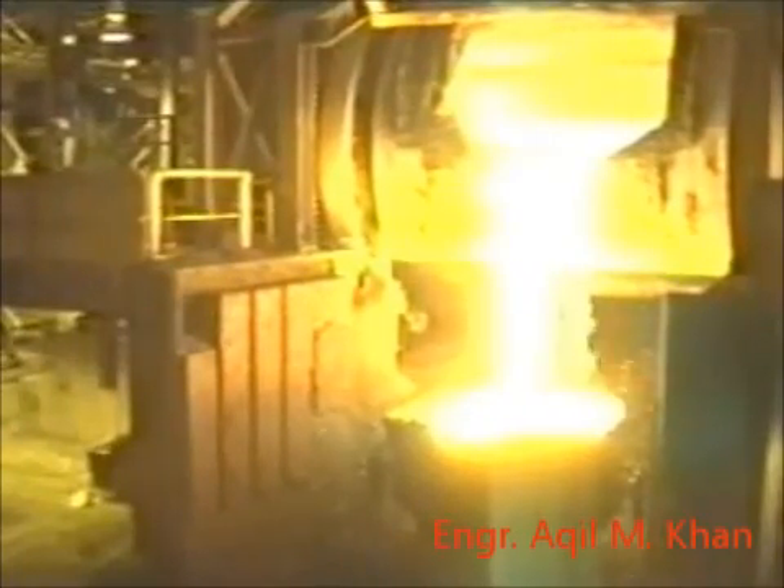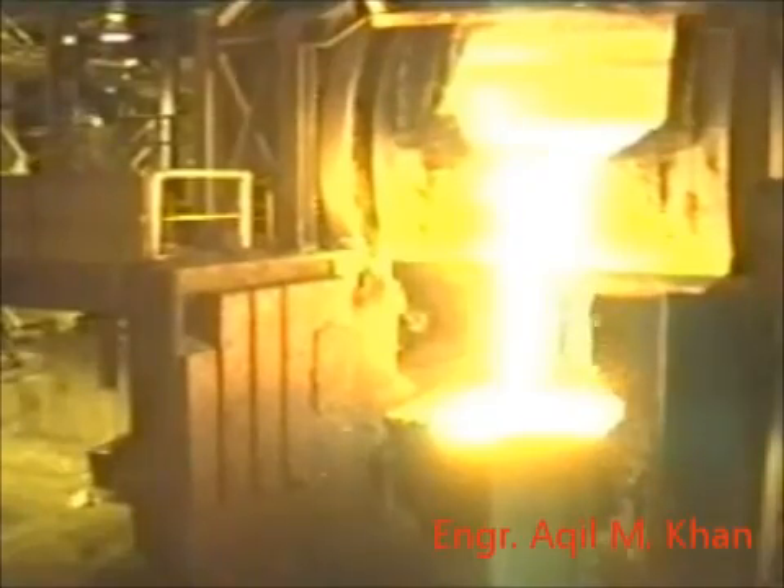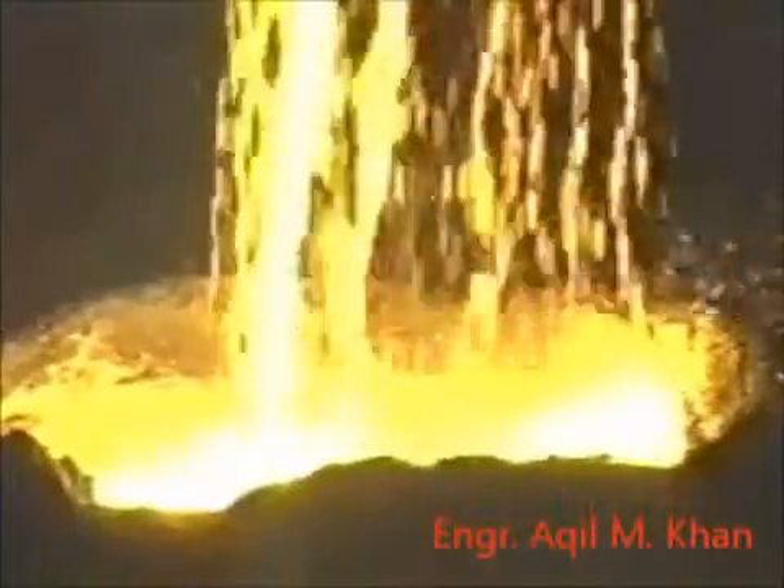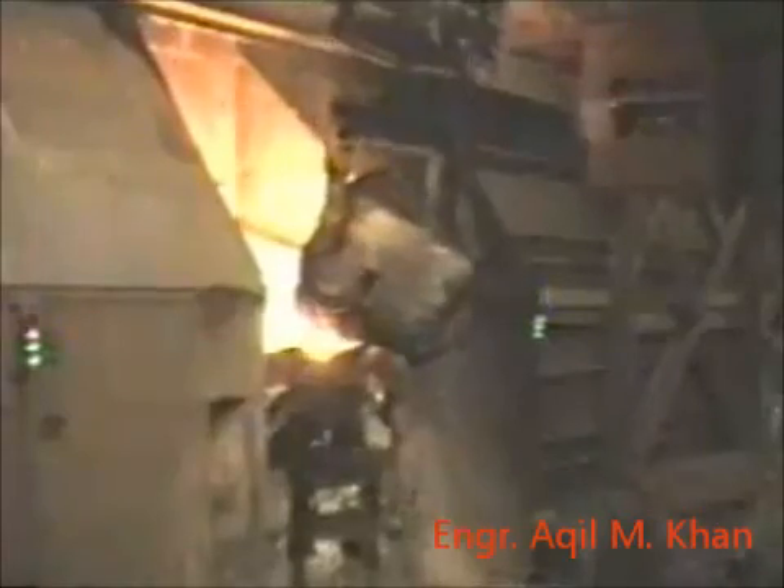In these vessels, air is blown through the bath. A good portion of the sulfur is removed, and the balance of the iron is skimmed off as slag. This slag is transferred back to the flash-melting furnaces to recover any remaining metal.